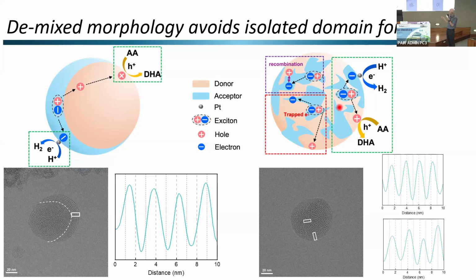So if you imagine a situation where we have an isolated either donor or acceptor buried in the center of our nanoparticle, there's no way that these charges are getting out. And it's particularly important for electrons. So if you've got an isolated acceptor domain here, this is a problem, and I'll show you the implications of this later. But here, this is an example of a really nice core shell particle. You see these beautiful concentric images here, hopefully, and then we have a more amorphous part here. Here we've got our intermixed structure, and we can look at the periodicity of the lamellar fringes here. You see very nice uniformity, and here are two distinct features of our donor and acceptor that we can see when we look at the images.